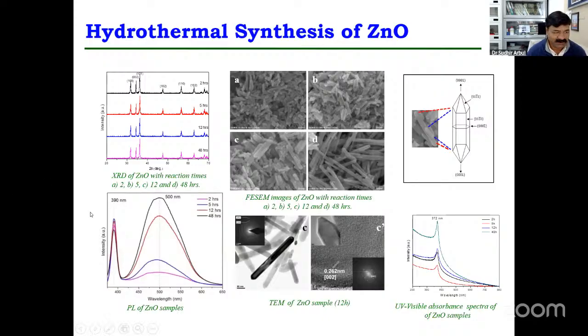So here we got two peaks, 390 nanometer band edge emission and 500 nanometer. This is due to the defect created in between this zinc oxide. So what is happening? The electron from the valence band goes to the conduction band. Few electrons come back directly, few are staying here. It gets transferred to here.